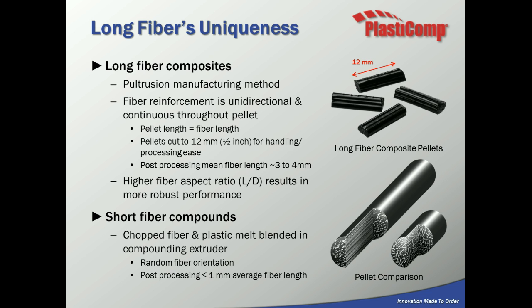The smaller pellet in the lower bottom right is a representation of a short chopped fiber pellet. That's made by taking random fibers and dumping them into an extruder with thermoplastic material and mixing them. That mixing process actually shortens those fibers, and you typically would get less than, let's say, 1 millimeter fiber length in the final part, which leads to lower mechanical properties.